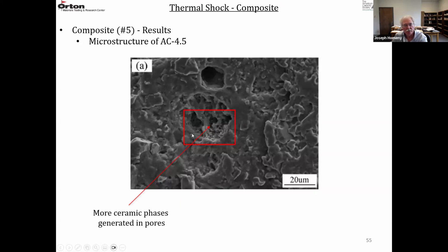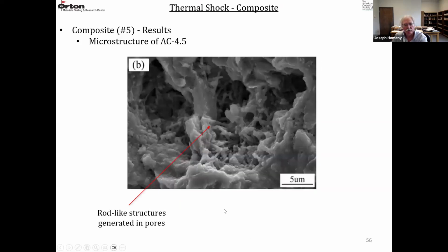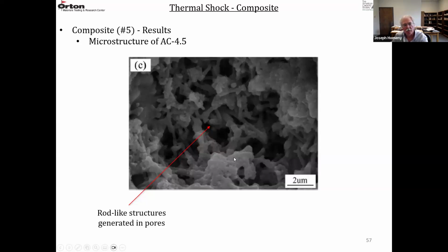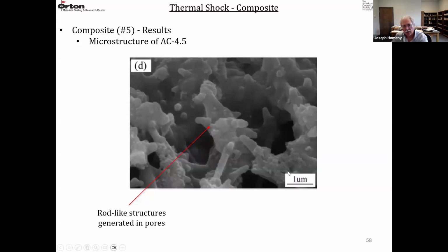This is AC 4.5. They're looking at the pores again, and there's more ceramic phases forming at those surfaces. And this is a higher magnification of an internal pore. And then they're starting to see these rod-like structures that are forming in the microstructure. And then this is an even higher magnification of AC 4.5. And you can clearly see the rod-like structures that are being formed in these materials. And just another even higher magnification of the same rod-like structures in the pores. You can see they're forming.